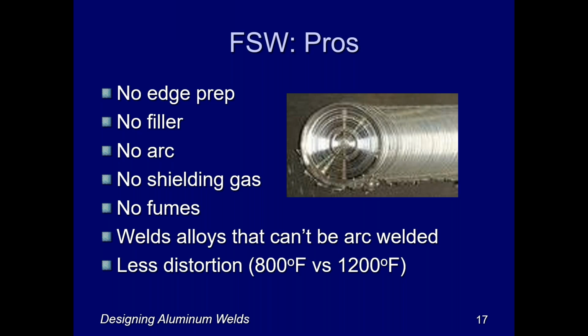Now, before we leave the welding processes, though, we'll talk about friction stir welding. Friction stir welding is a relatively new process, patented in 1991 in the United Kingdom, and it's a really slick process. There's no edge prep in making a groove weld, so you don't have to bevel the sides of the joint or the parts. You don't use any filler metal. You don't use an electric arc. Therefore, you don't need any shielding gas, and therefore there are no fumes. And you can weld together alloys that can't be arc welded.